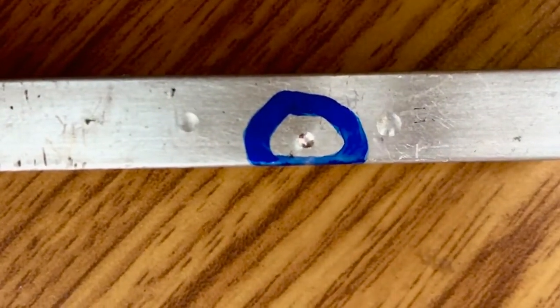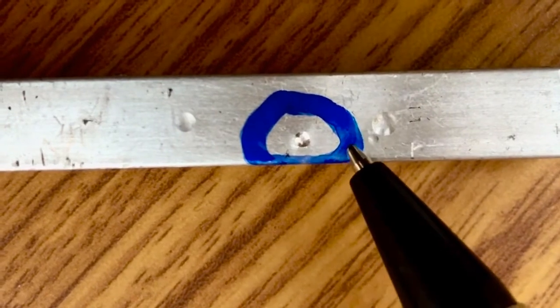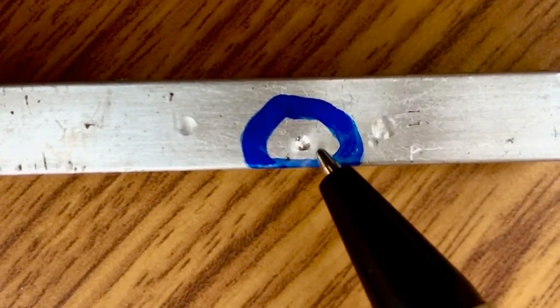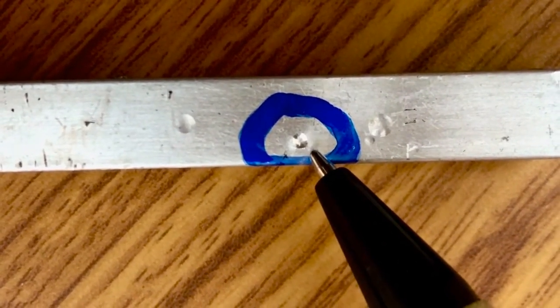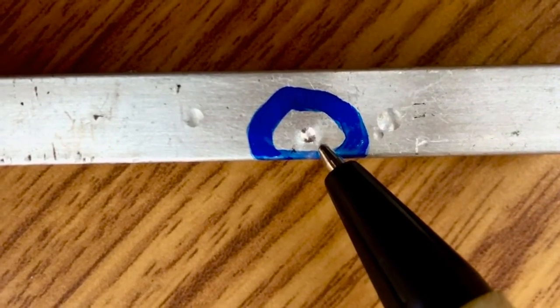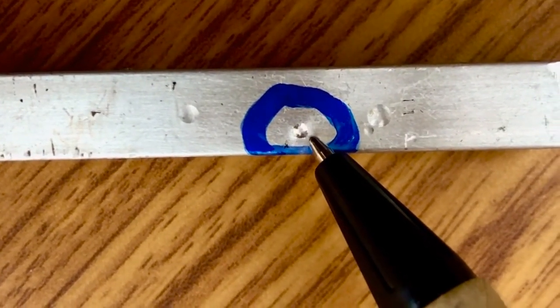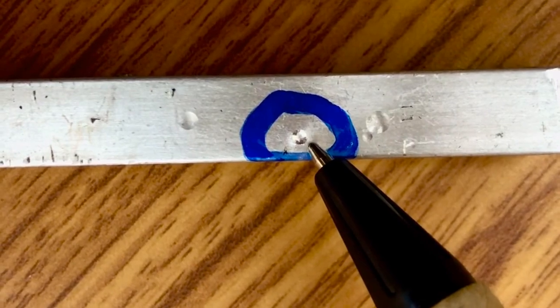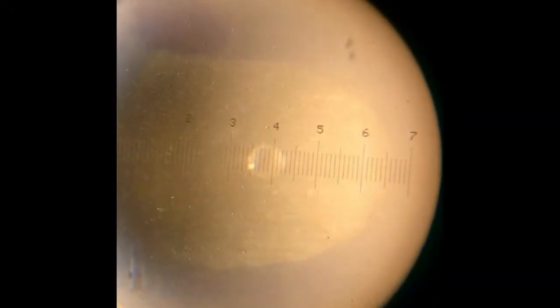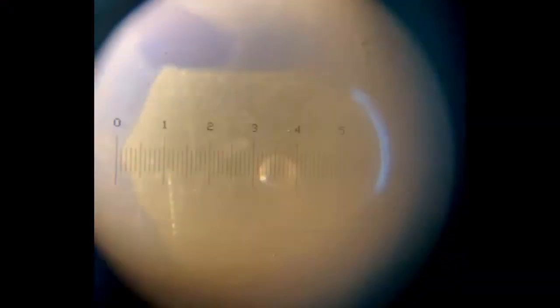After performing the hardness test as per the standard procedure, we have obtained this impression on the aluminium specimen. Now we are going to measure the diameter of this impression by using the microscope. Under the microscope, it is clearly visible that the impression diameter is approximately 1 mm.